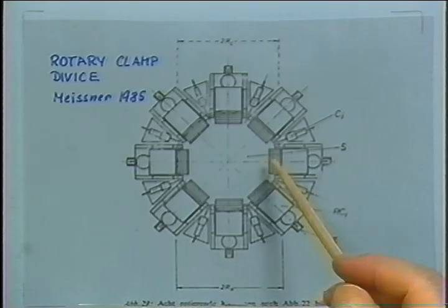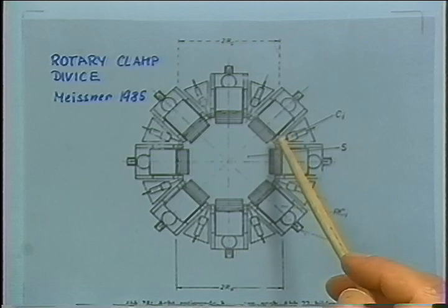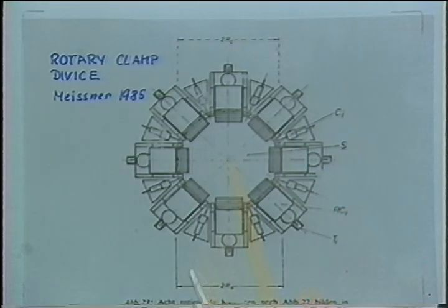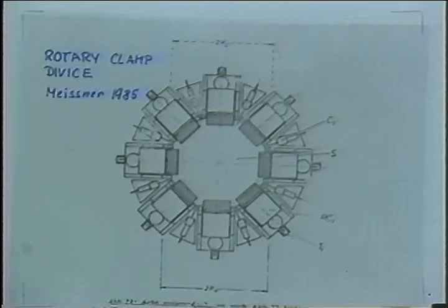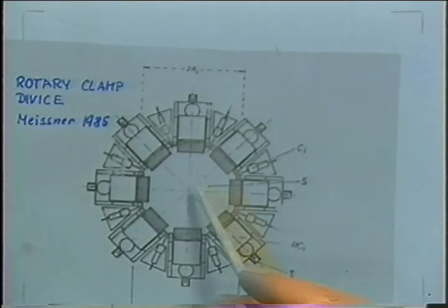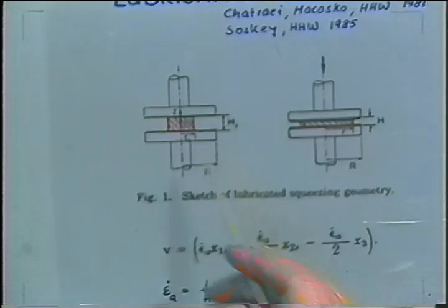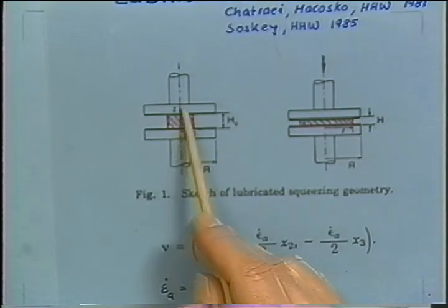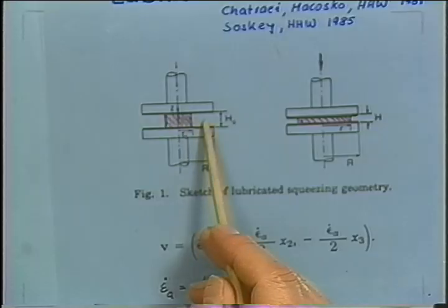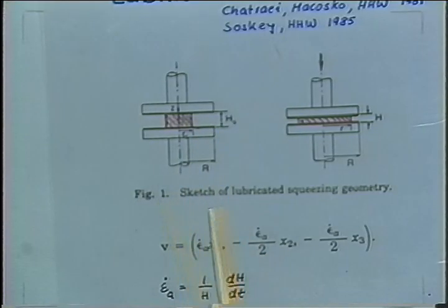The difference concerning the stress level is that there you're pulling on the surrounding, and the top and the bottom are at ambient pressure. So you have tension there and ambient here, while here we are pushing on the bottom and the top, and we have ambient on the side. So the experiments are done at a somewhat higher average pressure level, but otherwise everything is the same. But this containment helps stabilize the experiment at high rates.